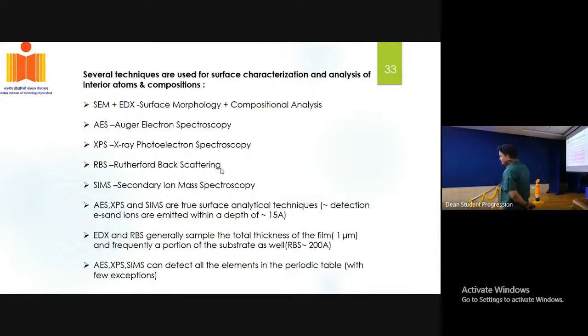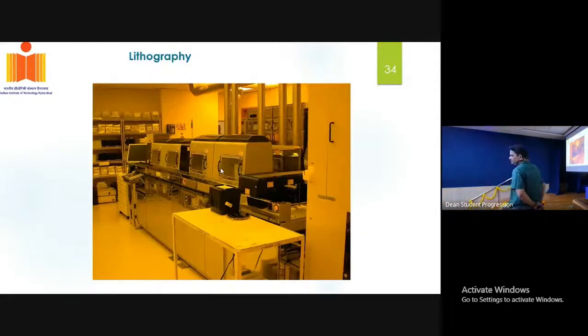The surface technique means that suppose you have a very ultra thin film, where the thin film thickness is of the order of 1 nanometer. If you want to characterize your thin film in a better way, you must use Auger electron spectroscopy, XPS, RBS, and SIMS. So now we know how to get the thin film. We have used 3 different techniques. One is the physical vapor deposition technique.